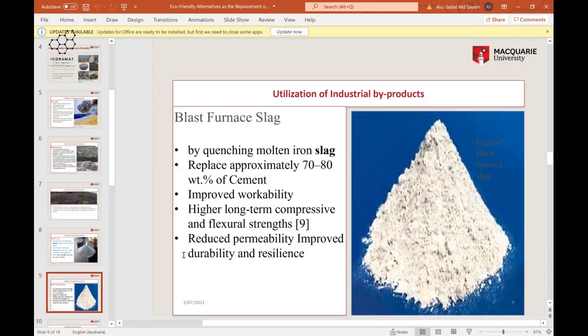We have another industrial product, blast furnace slag, which has a very good result compared to the others. It can replace around 70 to 80% of cement, and it has very improved workability. In the long term, it gives very high compressive and flexural strengths.